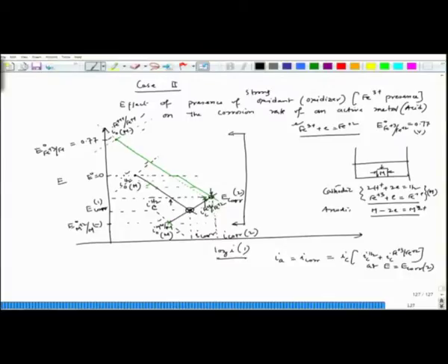But once we have Fe+3, the corrosion rate is increasing, but the rate of hydrogen evolution on the zinc surface is decreasing as compared to what it should have been without Fe+3 in the solution. So the hydrogen bubble formation on the metal is reduced somewhat, and this reduction is coming because of the depolarization effect.